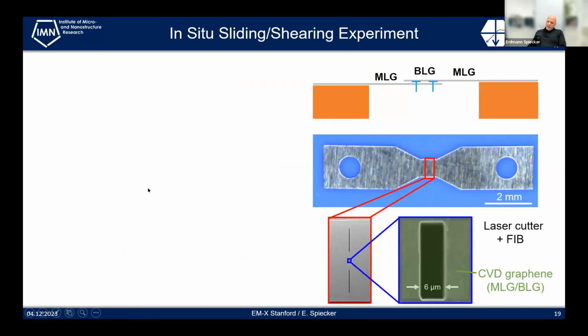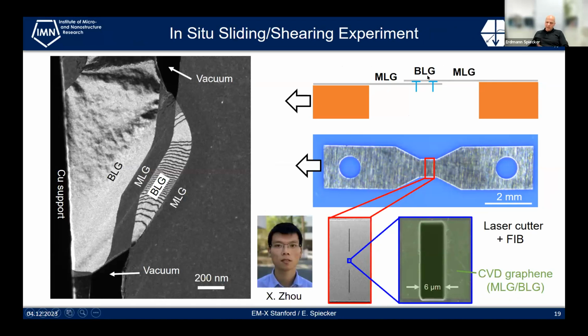So I come now to the experiment, and it works like that. So we made a dog bone sample for a conventional straining holder, and with a laser cutter we made some cuts and put some graphene, CVD graphene on top. If you now pull on the graphene, and it's a bilayer graphene and partly monolayer graphene, if you're lucky, you can achieve a situation as shown on the left-hand side. And it's really very difficult to obtain such a sample, but finally you find these sample regions where you get this configuration.